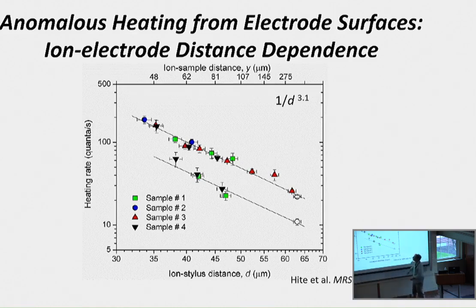What's the 2 lines difference here? I didn't understand. This one, what's the question? Are they the same slope, or why are they different? Well, one makes it just 2 different. We had this trap here, and then we cleaned it to try to reduce the background. And then we redid the experiment with the really nice sample and the really nasty sample. And they both heated the same. Does that make sense? Okay. So it's not temperature, it's just cleaning.